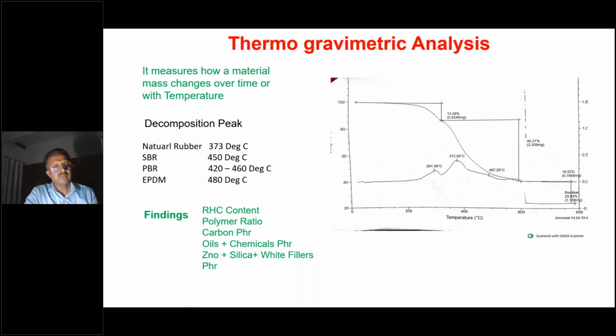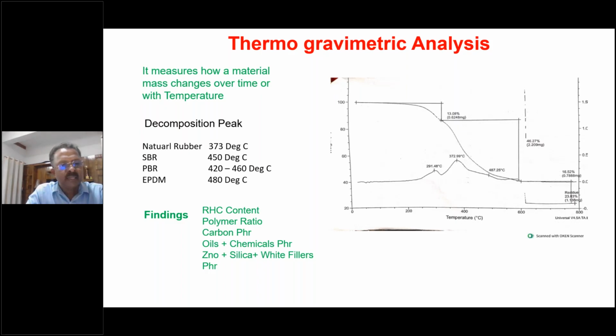Different polymers have different decomposition peaks. For natural rubber, 370 degrees centigrade. SBR 450 degrees centigrade. PBR 420, 460. So from TGA, we can find the rubber hydrocarbon content and polymer ratio from the area under the graph. And carbon phr, oils plus chemical phr, and the last residue will be the inorganics, zinc oxide, silica, and white fillers.